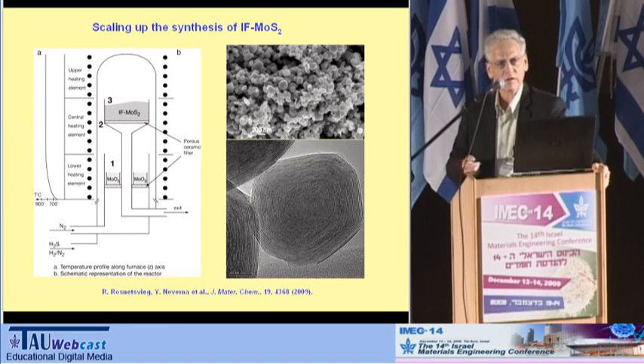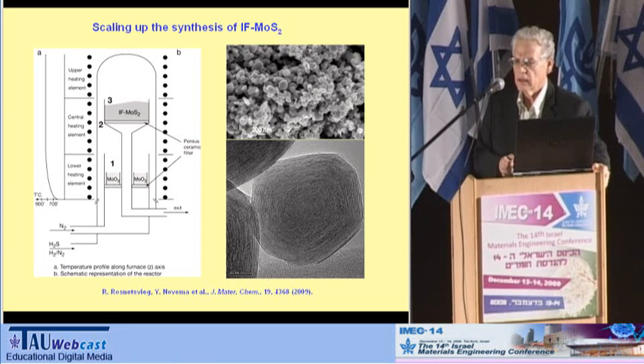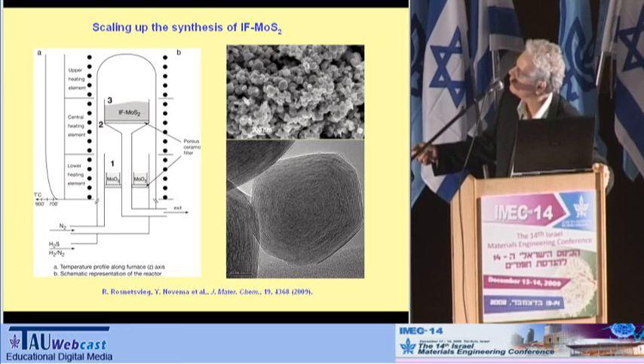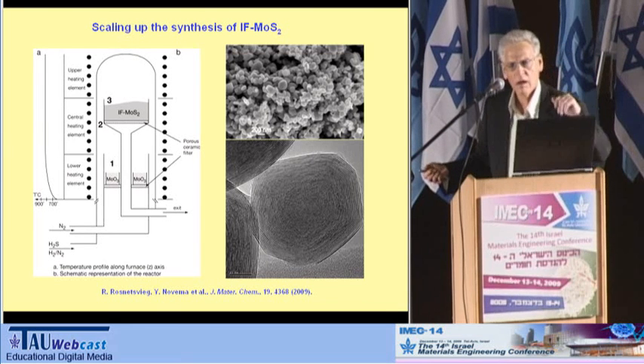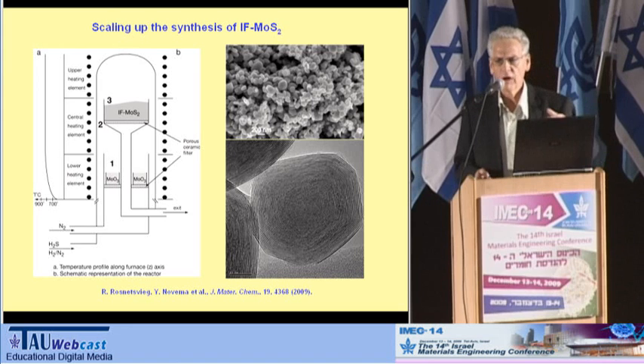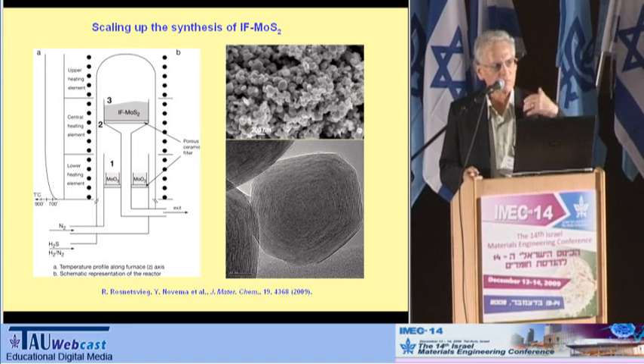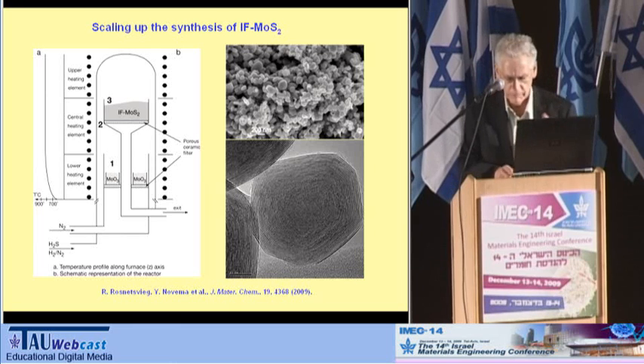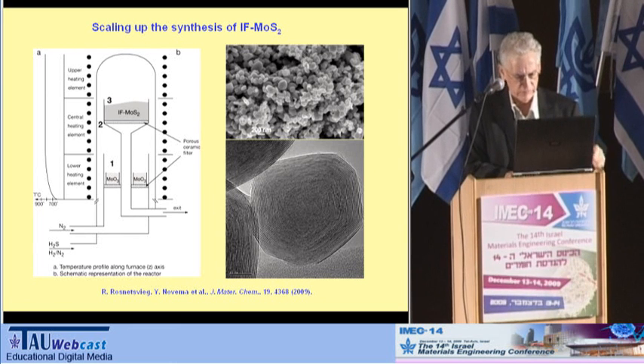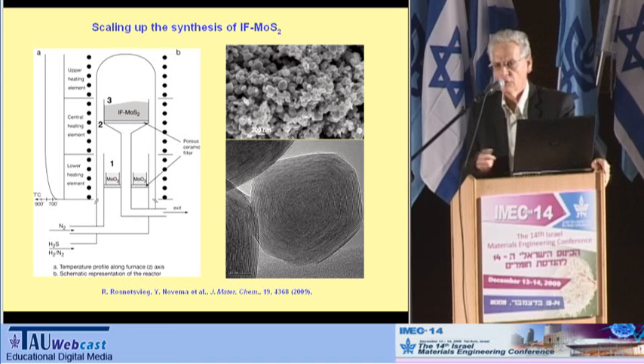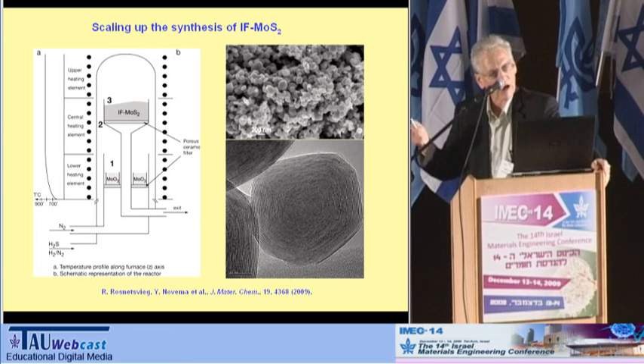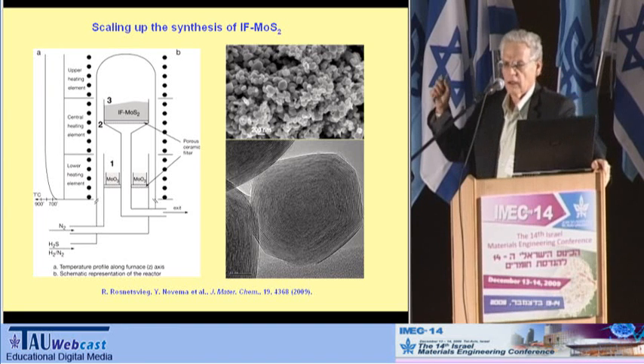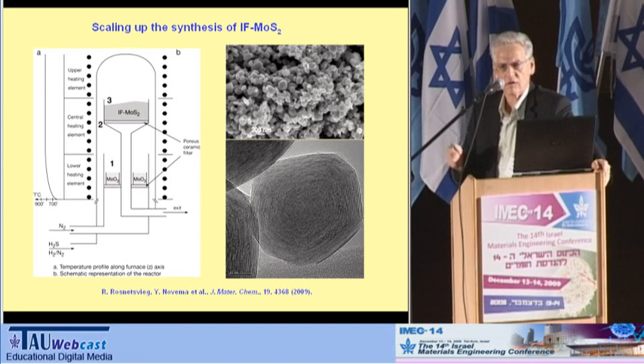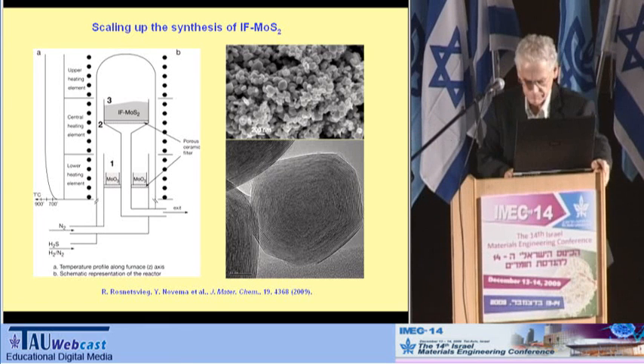In the case of tungsten disulphide, the reaction is fairly similar, but it's easier to control because we don't have to evaporate. We simply take tungsten oxide nanoparticles and do the same reaction. Therefore, the reaction with tungsten sulfide has gone further in terms of quantities. We can now make these nanoparticles basically in tons. It's just a question of price. Nevertheless, it's not a trivial reaction. The reactions have been known for many years, but the exquisite control of the size of the nanoparticles is the key issue here, because once they grow above 200 nanometers, they won't form closed structures like this any more.